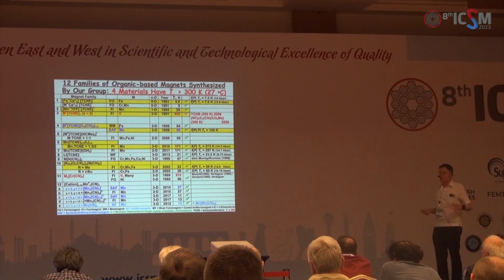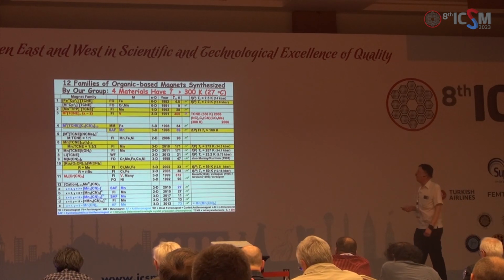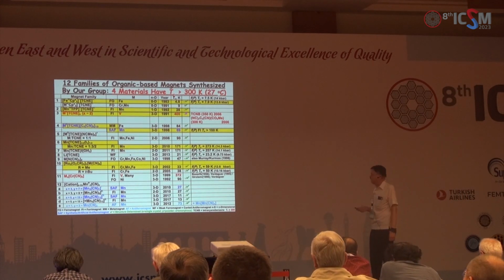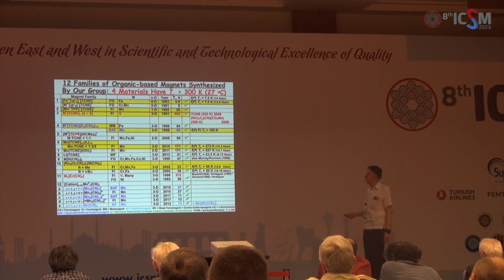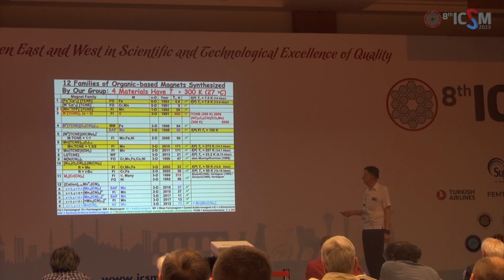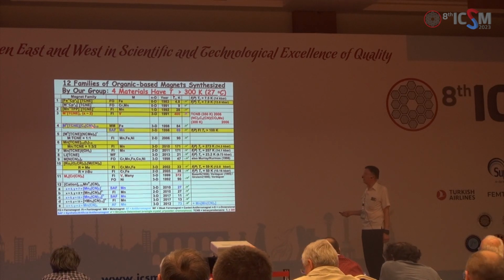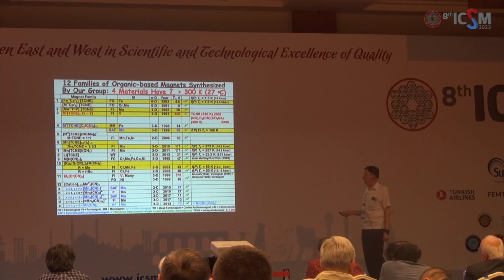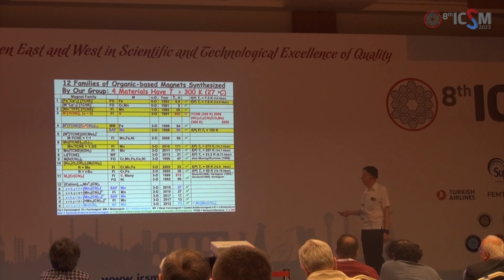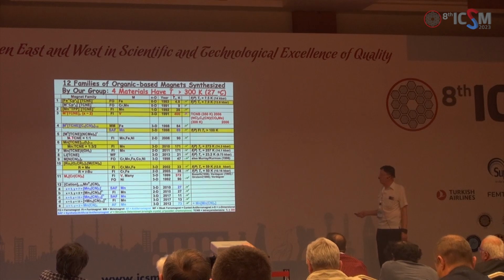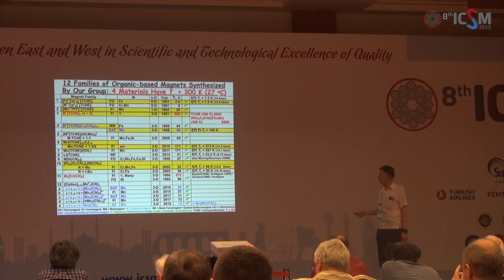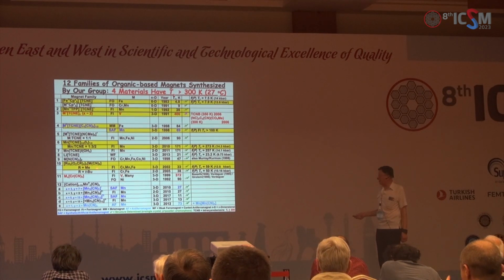To summarize, our group has made over 12 families of organic-based magnetic materials. The ones we talked about today are decamethylferrocene TCNE, manganese tetraphenylporphyrin TCNE, 2 TCNEs per vanadium, manganese with 1 TCNE—well, 2 TCNEs, the other being half of its dimer—manganese TCNE three-halves iodide one-half, and we talked about the ruthenium acetate.